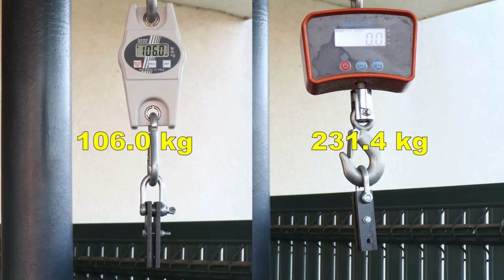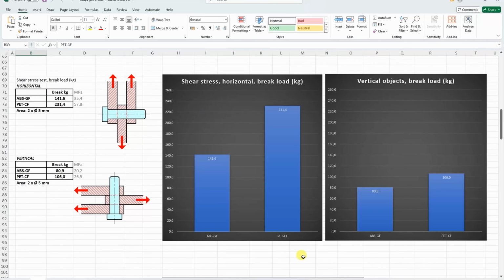And I know that I needed it here. Sheared correctly, but I couldn't find all pieces. Shear test with horizontally printed test objects, break load over 200 kilograms, so this is why I needed that stronger crane scale. With the vertically printed test objects, where the layer adhesion is important, also very impressive, over 100 kilograms the break load.